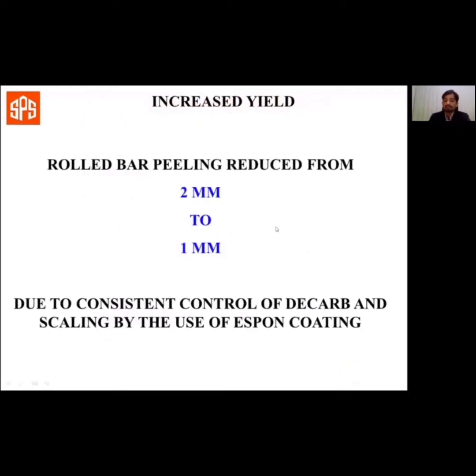In this case study, bar peeling was reduced from 2 mm to 1 mm as the coating consistently controlled decarburization and scaling. You can appreciate the material saving and time saving in this case.